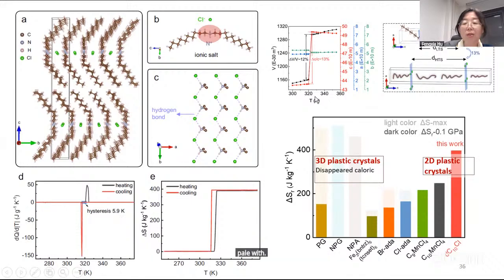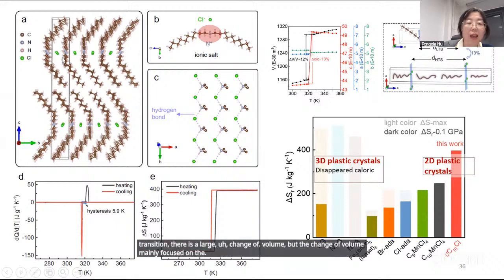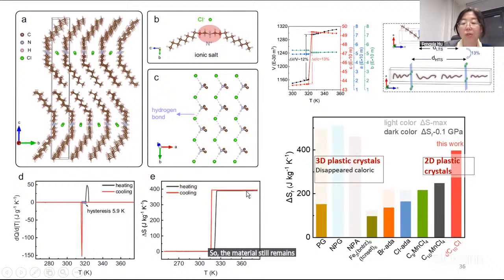Kelvin. And this is the result of XRD. We can find across the transition there is a large change of volume, but the change of volume mainly focuses on the c-axis. I mean, the ab plane remains nearly unchanged. The c-axis is here, so the extension of the c-axis provides enough space for the movement of the organic chain. So the material still retains a large entropy change.